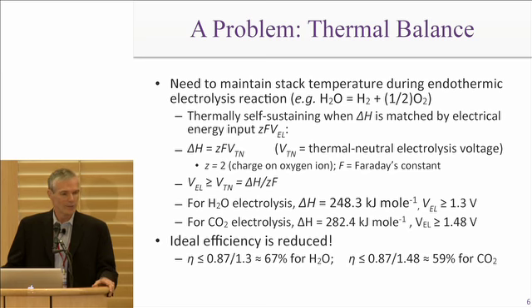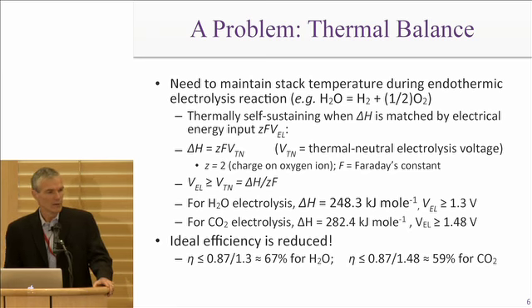So this is a high-temperature device, and when you're doing the electrolysis reaction in these devices, it turns out that the typical electrolysis reactions are highly endothermic. Okay, so if we take this one just splitting water to hydrogen and oxygen, if you look at the delta H for the reaction, it's highly endothermic. And what that means is that when you're operating the device, the electrical energy you're putting in during electrolysis has to at least match the thermal energy required for the reaction. Okay? And that equality is actually given by this expression here.